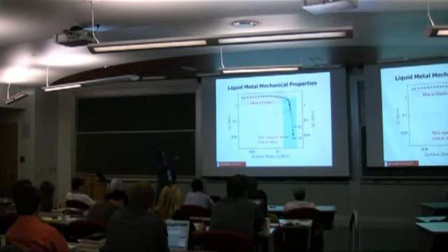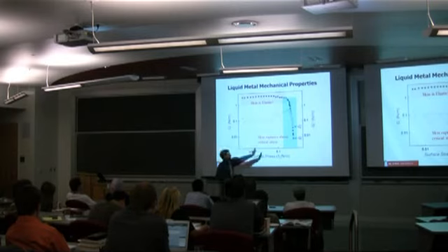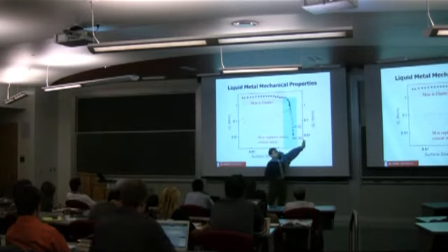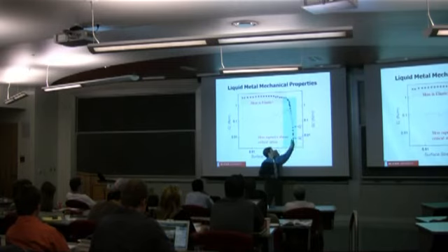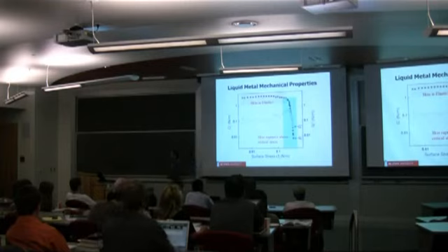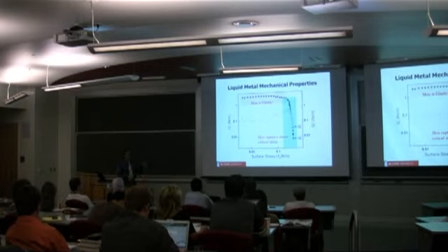But this is what's interesting. When you start pushing too hard, suddenly this drops very, very fast. And what's happening is you're breaking the skin. So if you push with force greater than this, the metal will flow. And if you push with less force, it will hold its shape. And so this kind of gives us a guide to allow us to flow the metal with certain pressures, but then have it stop flowing when you're below a certain threshold.